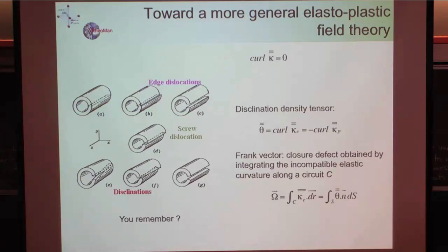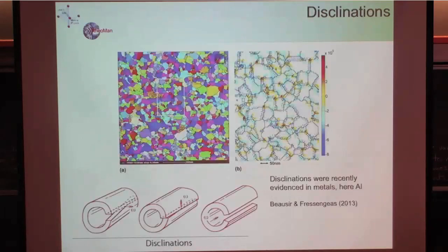They were already proposed theoretically by Vito Volterra in his original paper from the 20s. And he was already considering the possibility of translational defects, which became popular as dislocations, and rotational defects, which became completely forgotten as disclinations. Not completely: people in liquid crystals use disclinations a lot, because they have weak materials. We usually considered that it was not useful. But in fact, it may be.